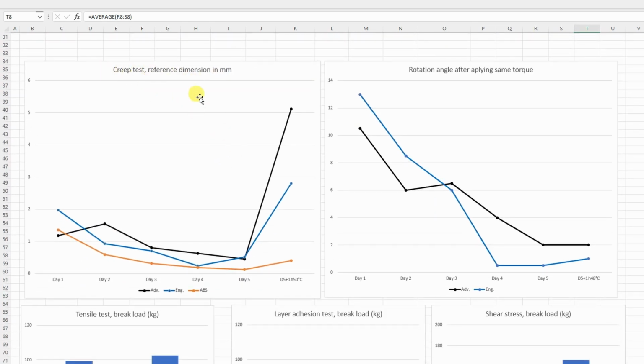The creep test, the bending creep test. Actually all these values are very low. I checked the earlier videos, and only at 50 degrees Celsius inside the oven I can see a little bit more difference. The most creeping had the Advanced PLA, then Engineering PLA, and almost no creeping of the ABS.